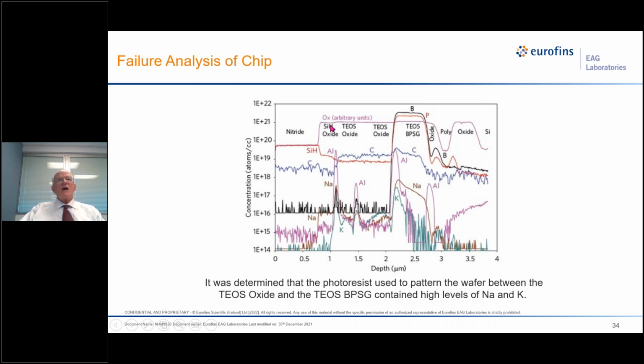But I know it's a TEOS oxide, and we follow carbon, and the carbon goes up. Remember, TEOS is tetraethyl orthosilicate as a starting material, so some of the carbon gets incorporated into the film. We have a BPSG here, so we follow the boron and phosphorus levels. Another oxide, polysilicon layer, oxide here, and then the substrate. We have spikes of aluminum. This is where the metallizations were done.